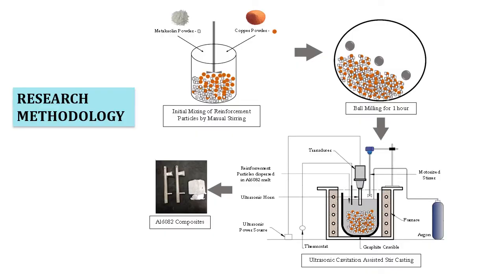It is a well-known fact that ceramic particles, while reinforced in aluminum composites, will result in reduction in ductility, even though there will be increase in tensile strength and compressive strength, hardness, etc. So, in order to avoid that, these ceramic particles may be premixed with a metallic powder so that the ductility may be retained. From various literature, the author has come to a conclusion that, based on the different metallic